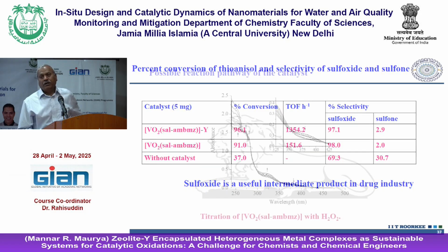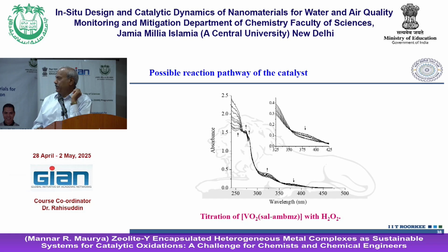Now, to propose the mechanism, this is one of the important parts, you take the help of the homogeneous catalyst. When you titrate, we record the UV visible spectra of the compound at different concentrations of H2O2. What do you see when you add dropwise a methanolic solution of H2O2 to the solution of metal complex? You see the spectral changes, and during the spectral changes you find at least 2 to 3 isosbestic points, and that suggests that the vanadium compound VO2 is converting into a peroxide species.